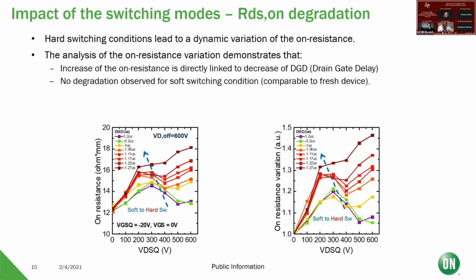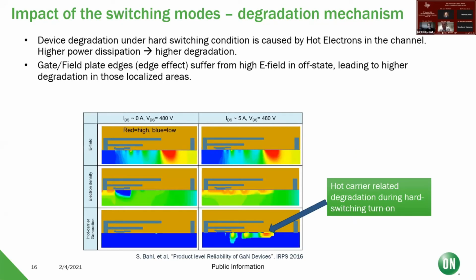And then last, I just wanted to show this cross-section simulation of heat distribution during switching, and how much is happening at the surface of the GaN in this case. It's affected by the field plate design in determining the static electric fields. And so the design can affect the statics of it, and then during the operation, you have to start modeling the dynamics of the hot electrons in the channel to really predict the degradation of the RDS(on). And it can be contained to smaller and smaller percentages as time goes on, but that goes in tandem with understanding the material better, which was one of the early statements.